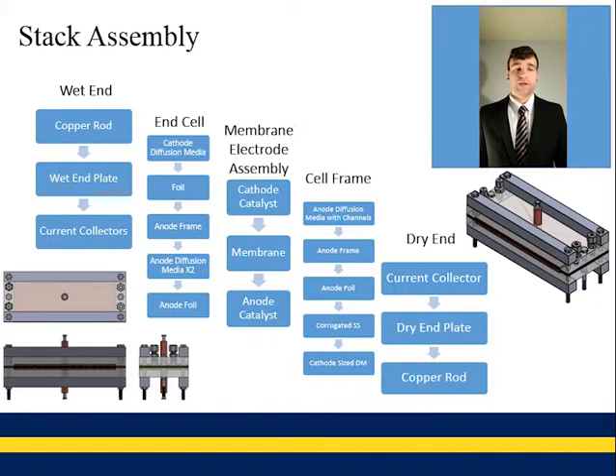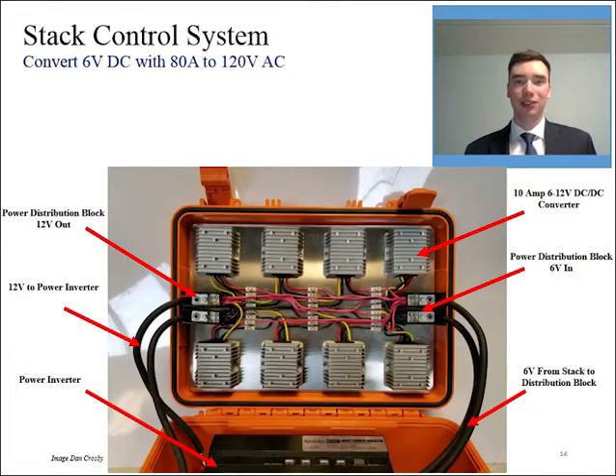Above this, you have an end cell, which will stay with the stack the entire time you're using it. This is an anode foil, anode diffusion media, another anode diffusion media, anode frame, then foil, then a cathode diffusion media. Then finally, to top it off, you have your wet end assembly, which is a current collector, wet end plate, and copper rods, all of which is fastened together using various bolts and screws. Now to add more cells to the stack, all you need to do is put another cell frame and membrane electrode assembly inside of your stack.